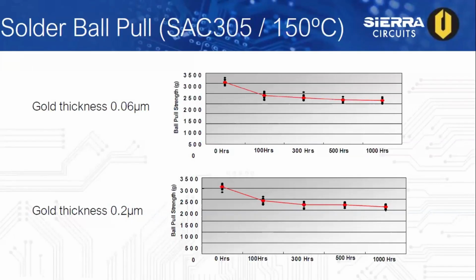Now, solder ball pull testing was also completed using SAC 305 at 150 degrees Celsius with samples at 2 different gold thicknesses that you can see here on the left, 0.06 microns and 0.2. And as the graph shows, if you overlap those, you can pretty much see that there is insignificant difference in the ball pull strength when comparing both of those gold thicknesses.